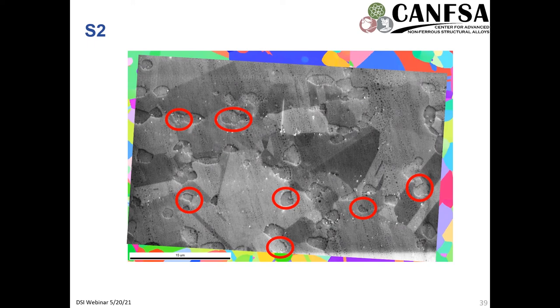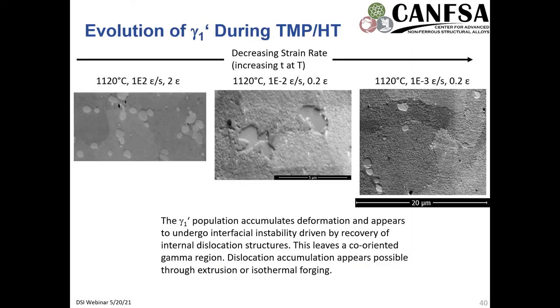And so now that we've established the effects of dissolution of the primary gamma prime to incur a stable gamma shell that's co-oriented with the primary gamma prime, one of the effects that we're interested in is deformation at these high temperatures. We have here three different micrographs showing various strain rates. And there are two different contributions here.